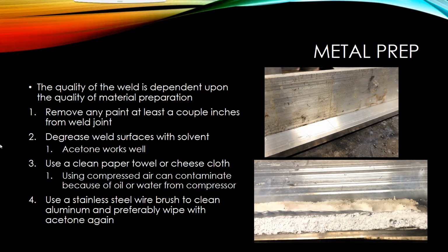So I got a couple pictures here, and the top one is the T-joint before it was welded. Basically, it's really dirty. There's a whole bunch of gunk on here. I just wanted to show an example of what would happen if you didn't prep that material. So I went ahead and welded it, and then I broke that weld to look on the inside. The weld actually looked okay from the visual appearance up above, but once you broke it open, you have all these little spots. You see these circles of porosity. So you want to eliminate any porosity that you can, because that's going to cause a defect in your weld.